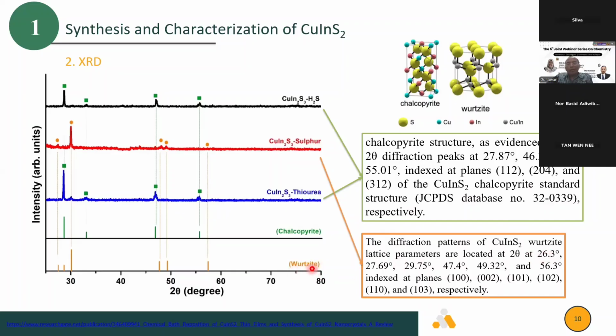And the diffraction pattern of copper indium sulfide with lattice parameter located at 2 theta 26 here. Wurtzite here. 26, 27, 29, 47, and so on. So for copper indium sulfide deposited by using sulfur here, there is a different character. So yes, it has a character of wurtzite. Meanwhile, for copper indium sulfide from H2S and thiourea, it will have chalcopyrite type here.